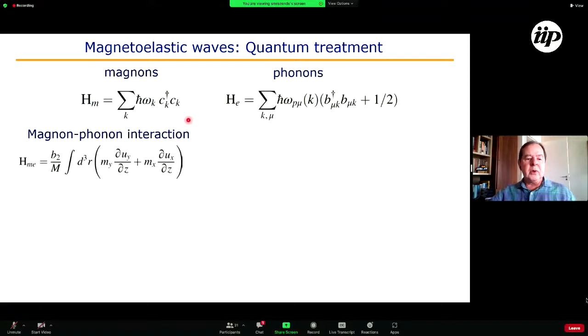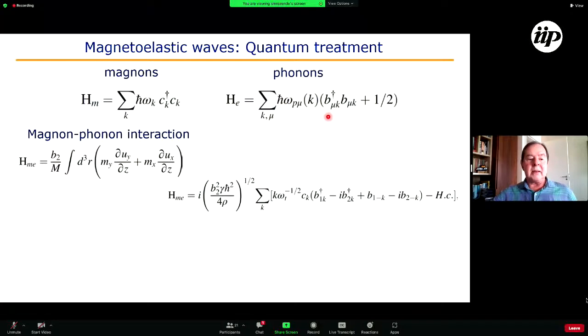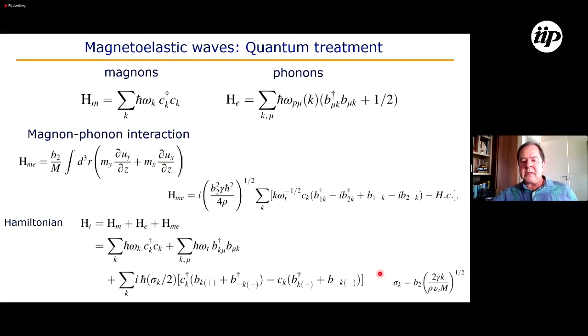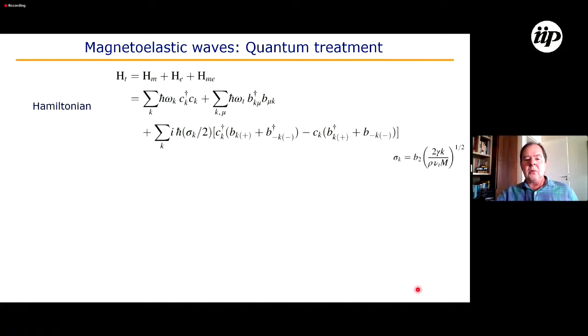Hamiltonian. If we take the magnon-phonon interaction that I showed before, and we make a transformation from the magnetization to the magnon operators, and from the displacement to the phonon operators, one can show that the magnetoelastic Hamiltonian has terms that involve products of the magnon and phonon operators. And so the total Hamiltonian is the sum of the magnon, the phonon, and the magnon-phonon Hamiltonian. This parameter sigma_k is proportional to the magnetoelastic interaction given by this expression here. So we have this Hamiltonian for coupled magnon-phonons.